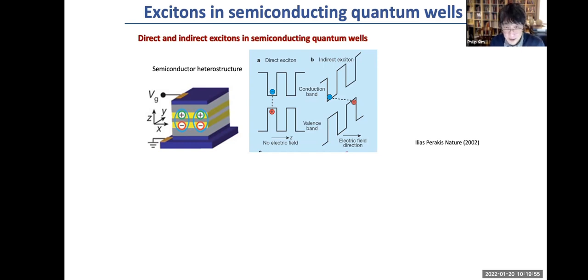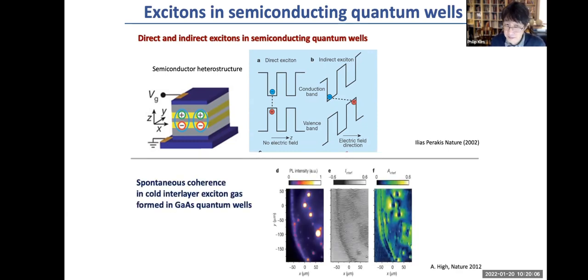And for this type of exciton, since the electron and holes are separated spatially, the recombination rate is low, therefore they can live quite long. Using this type of interlayer exciton, the semiconductor physics community developed a way of pumping a lot of interlayer excitons optically, and they start to see that these interlayer excitons can develop self-coherence, which is the very first step toward realizing this exciton condensation.